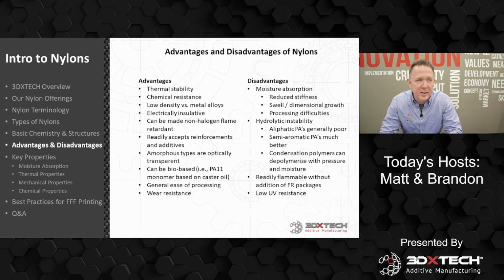And then, of course, what we all see all the time, anytime you've printed wet nylon, you have processing difficulties. So there'll be steam, bubbling, surface defects, interlayer delamination, general poor mechanical strength. Then there's hydrolytic stability, which is a close cousin to this moisture absorption issue. But what this is, when the material absorbs moisture and is under temperature and pressure, you can actually depolymerize or unzip the backbone. And you'll end up with degraded properties. You really can't come back from that when you dry it back out.